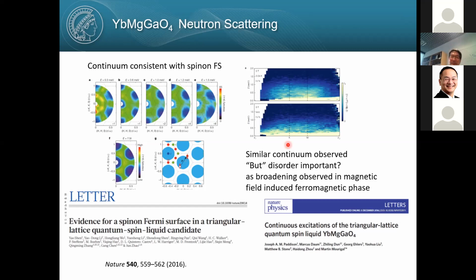And the other group, after 1 year, reported a quite similar feature, extended broadly over Q and energy, quite similar to the previous report. But in this specific case, they applied a magnetic field and made the compound ferromagnetic. Then you are supposed to see a sharp magnon dispersion line. But somehow, even in the ferromagnetic phase, those people observed broadened magnon excitation, like a continuum, and so they suggested this disorder due to the mixture of magnesium and gallium might play some role.